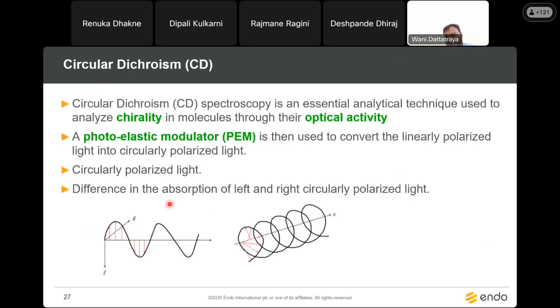One of the most important techniques for peptide characterization is circular dichroism. Circular dichroism is based on the chirality of the molecule and optical activity. In this, what will happen? We pass linear light through this instrument. There is one module in this instrument, a photoelastic modulator. What will the photoelastic modulator do? It will convert linearly polarized light to circularly polarized light, because linearly polarized light will not give any spectra or observation in the result. So we have to convert linear light into circularly polarized light, and for that purpose we use the photoelastic modulator.